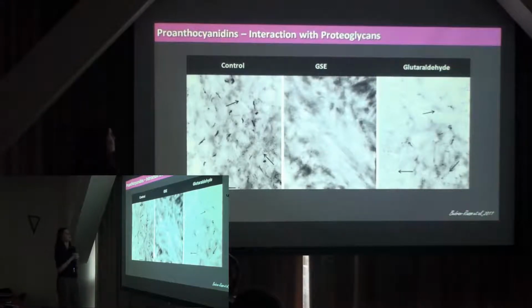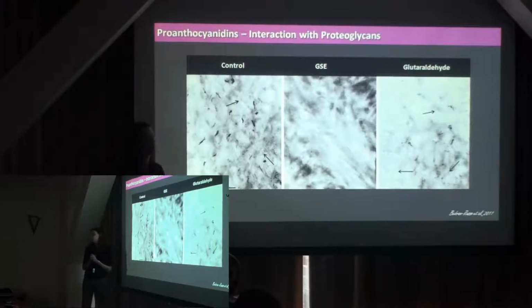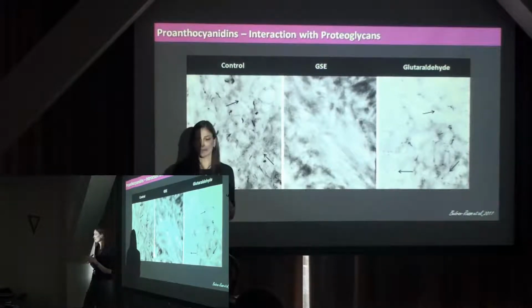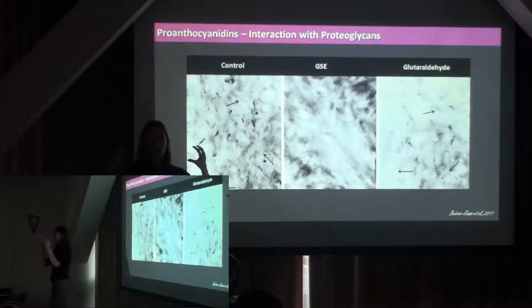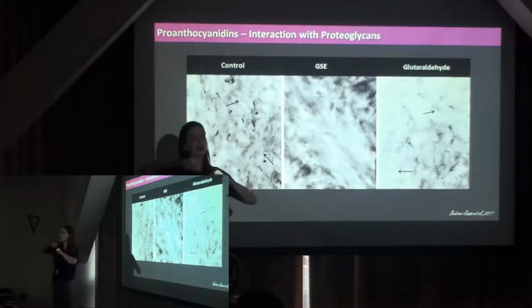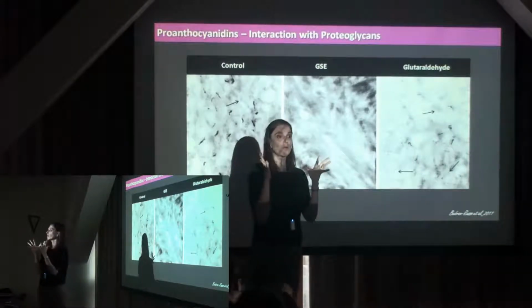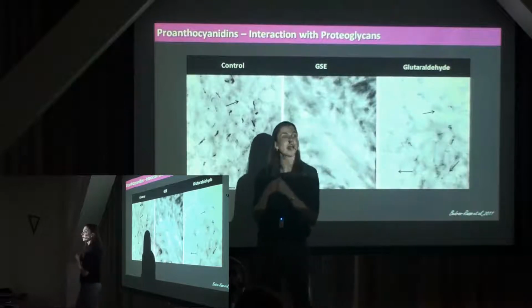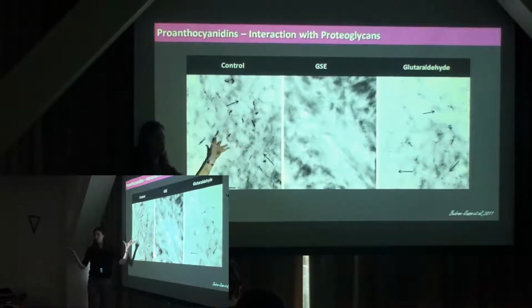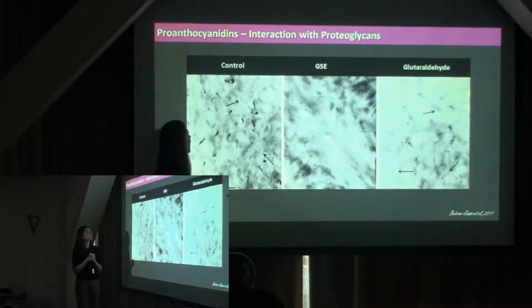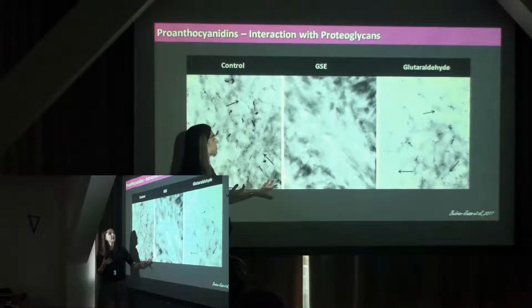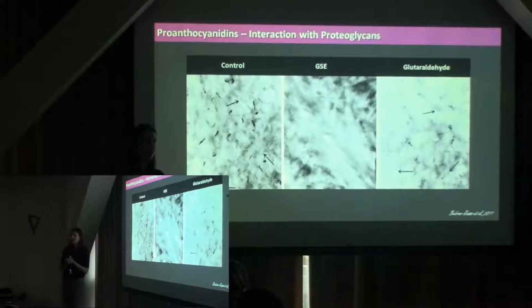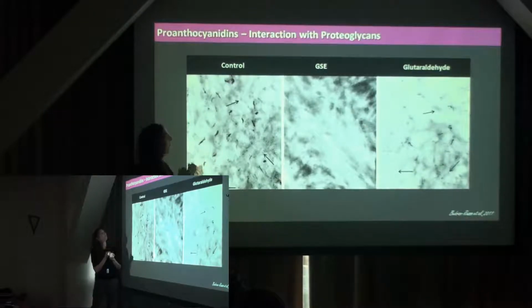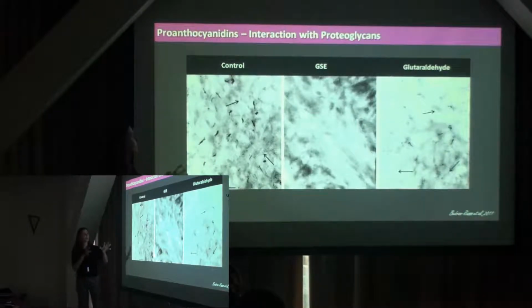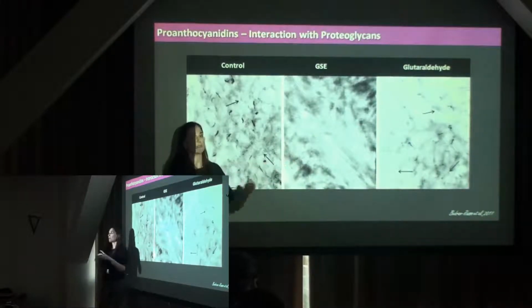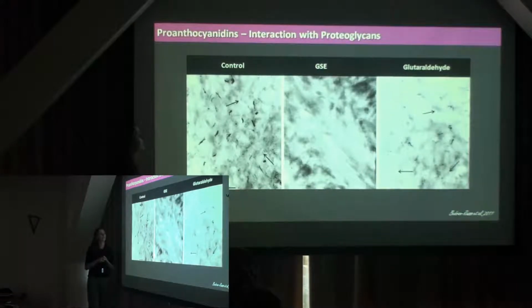What we also learned during the process of working with these proanthocyanidins is that they also interact with the proteoglycans. Proteoglycans are proteins with a core protein and these glycosaminoglycan chains. The glycosaminoglycan chains are very important because they're highly hydrophilic, so they're the ones that keep the tooth hydrated. We noticed this by mistake, actually doing some FTIR analysis, trying to characterize these collagen crosslinks, and then we realized that all the proteoglycans were gone. So there is a mechanism by which these proanthocyanidins have been removing these GAGs, and probably that's the reason why it may also be affecting the properties of the tissue.